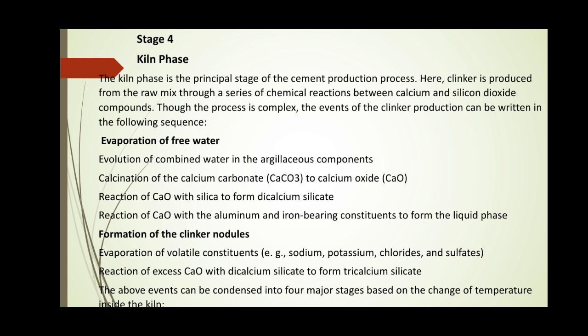Evaporation of volatile constituents, that is sodium, potassium, chlorides and sulfates. Reaction of excess calcium oxide with dicalcium silicate to form tricalcium silicate. The above events can be condensed into four major stages based on the change of temperature inside the kiln.